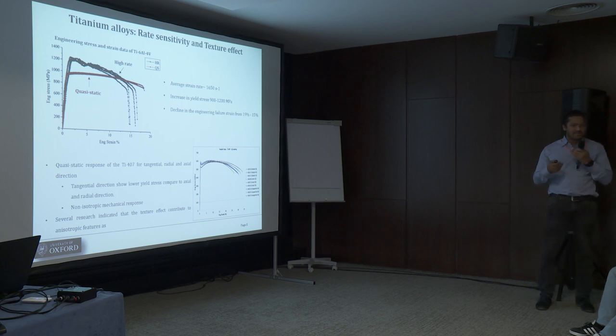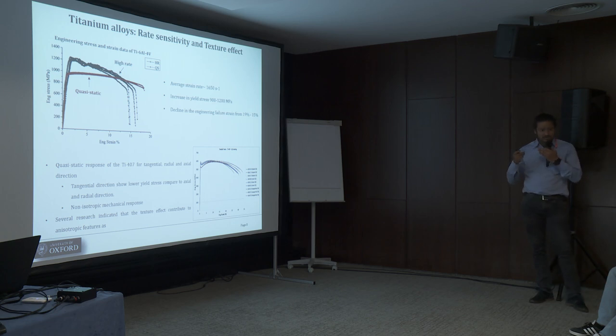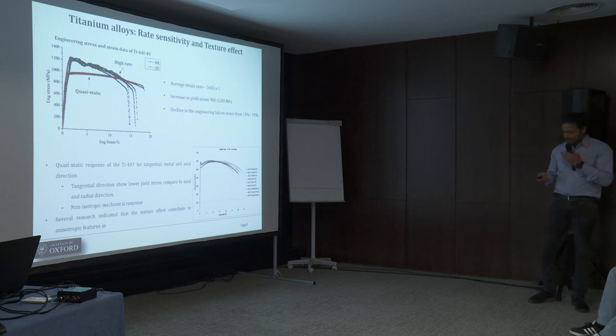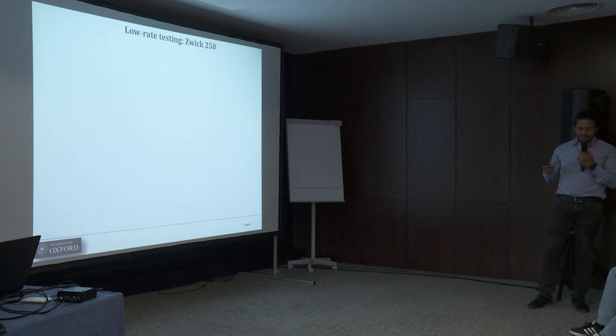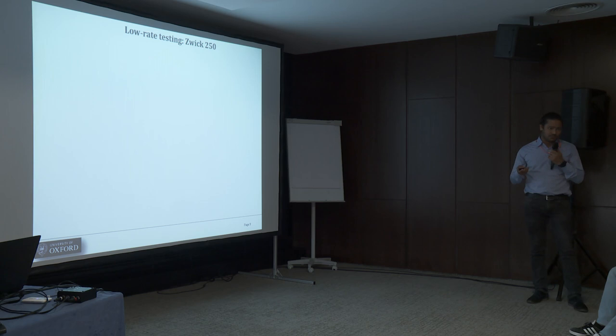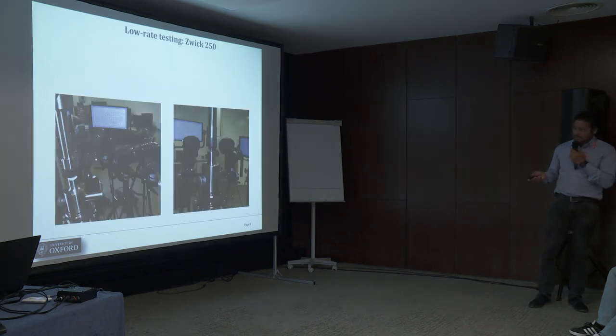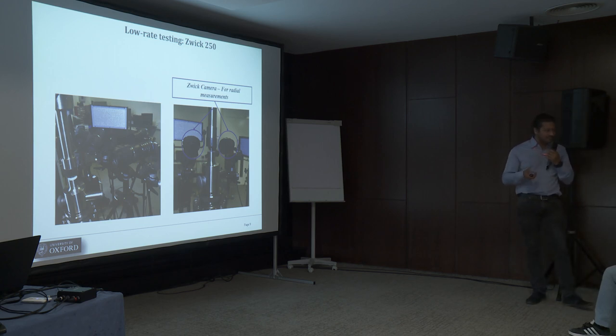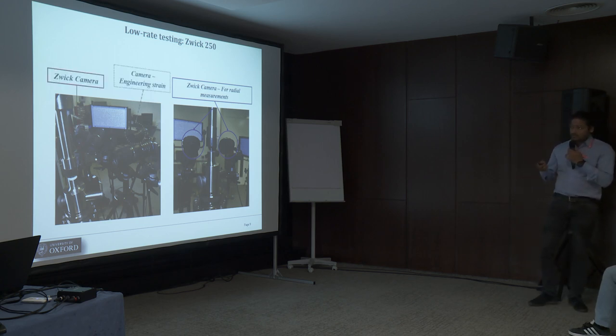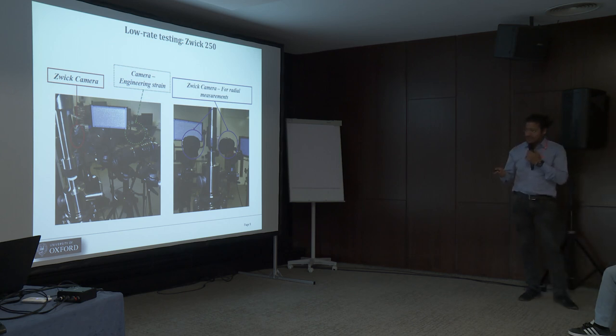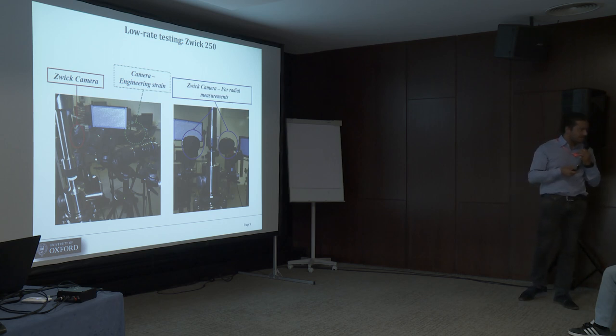We wanted to come up with an experimental setup to evaluate the elliptical cross-section during necking. For low rate testing, we selected a Zwick screw-driven tensile machine equipped with four cameras: two cameras dedicated to extracting diametrical contraction information, one camera to capture elongation throughout the process, and one Zwick camera triggered with the machine to synchronize all data from the other cameras.